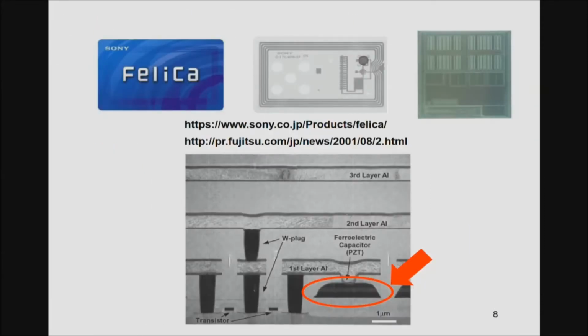So okay, ferroelectric is great, but I have to understand its challenges. The challenge is the process, basically CMOS compatibility of this material. Usually perovskite type material has been used, but the problem is perovskite material is usually designed really thick, and it requires a noble metal electrode, which is really hard to pattern. Retention and endurance are also other concerns. So these are the challenges for the conventional material.